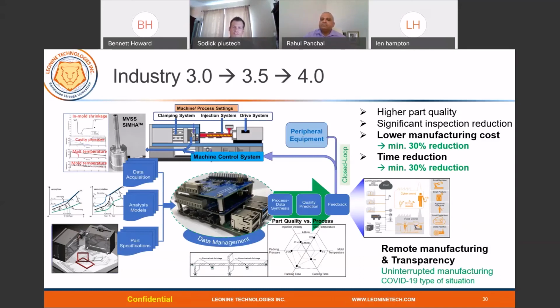All right. Will these sensors handle the mold temperatures that PEEK material requires? Right now, the sensor can handle up to 120 to 150 degrees centigrade, and one of our next goals is to increase that, to a melt temperature above 300 degrees C and a mold temperature above 150 degrees C. I know there are certain materials like PEEK or Ultem, which are specialty high temperature materials. A lot of electronics products use these materials. Medical devices, definitely implantable devices, use Ultem and PEEK quite often. One goal is to make the operating conditions as wide as possible, so you can utilize a wide range of different materials.